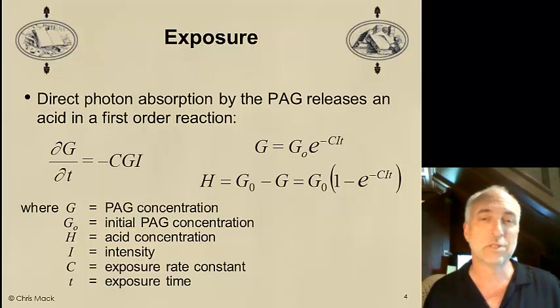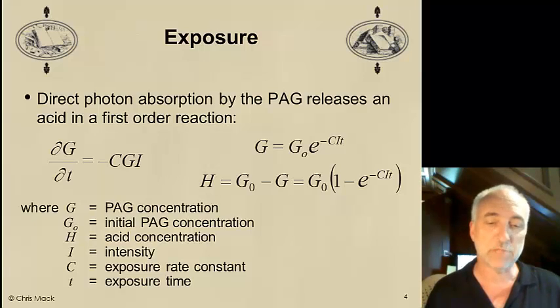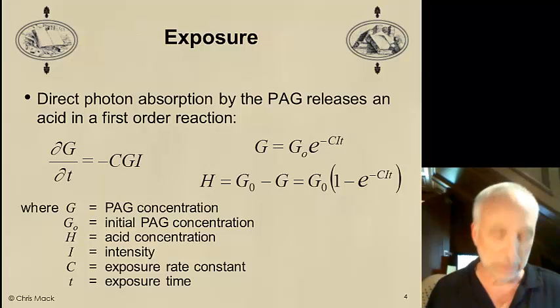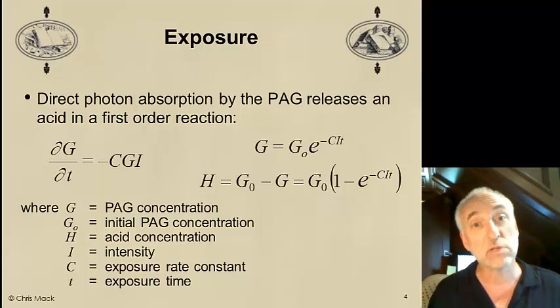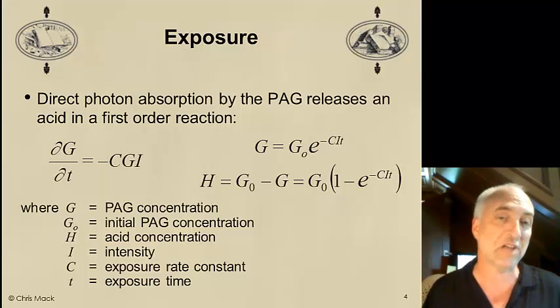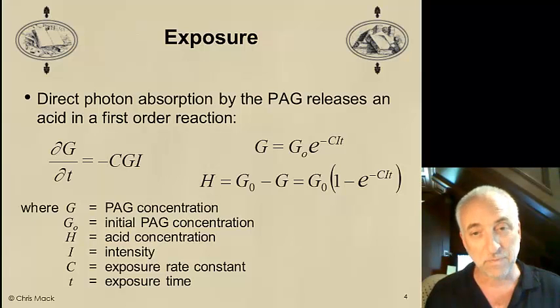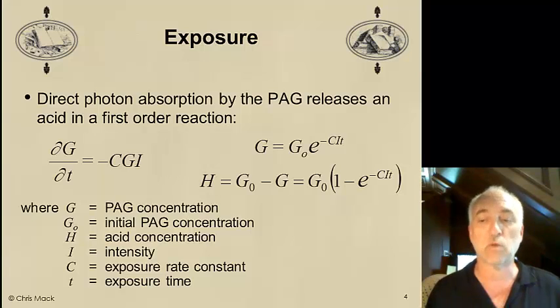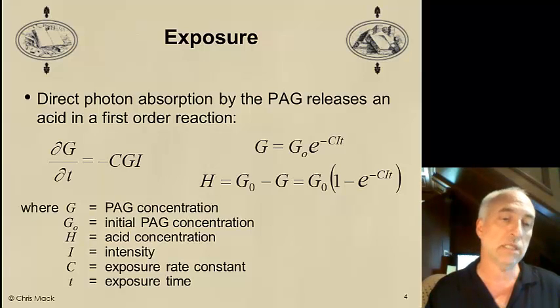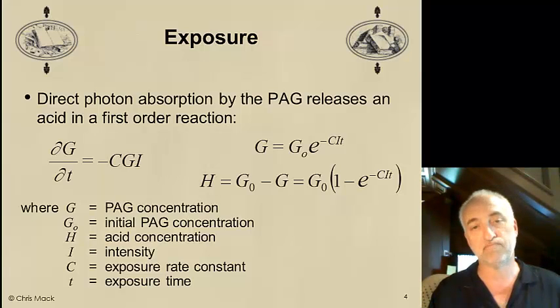Well, we're going to use chemically amplified resists at 248 and 193, and these resists do not bleach. They have A values of 0. As a result, the assumption that intensity is constant through the entire exposure process is a very good one, and these equations, in fact, are quite accurate, unlike the D and Q equations.